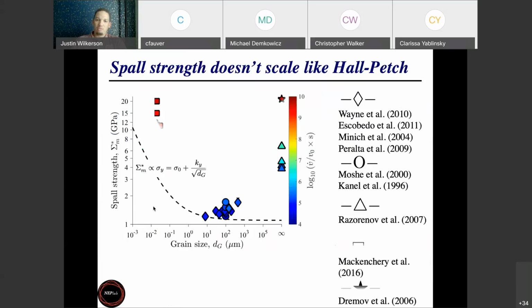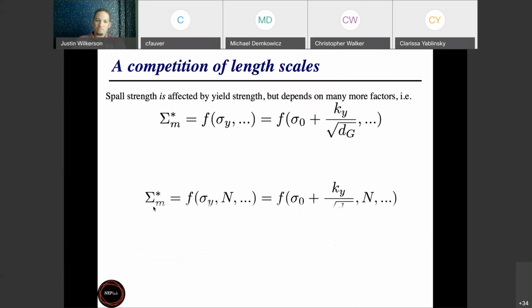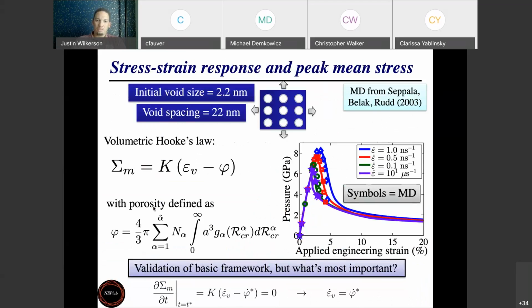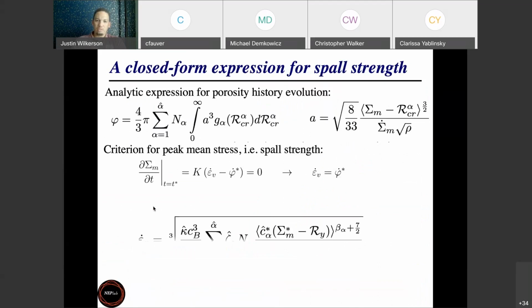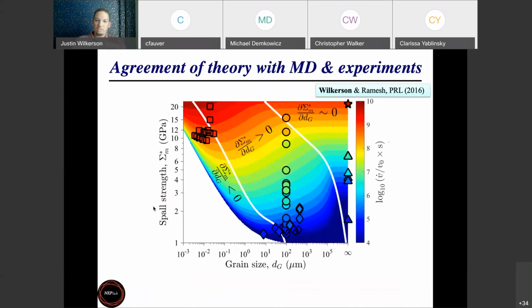So I'll skip through how we do that, but at the end of the day, we are able to get a fairly good agreement between experiments and the calculations. So these symbols in here are all experimental measures, and then the background contour plot is our theoretical and computational predictions. And so when the colors agree, that means that there's a good agreement between experiment and model.